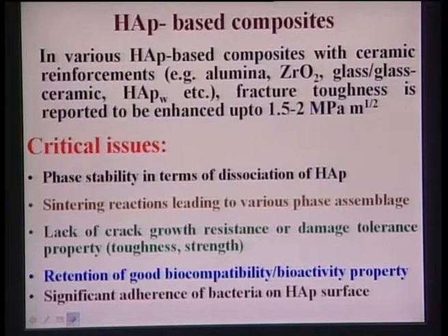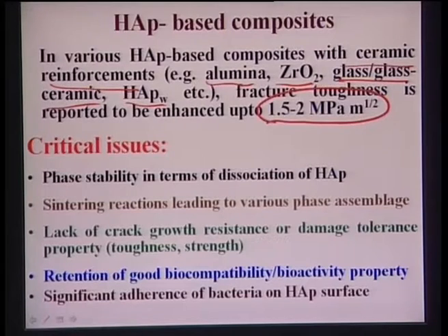Now, in various hydroxyapatite composites, particularly with ceramic reinforcements like alumina, zirconia, glass or glass ceramic, or hydroxyapatite whiskers, fracture toughness is reported to be enhanced up to 1.5 to 2 MPa square root meter. Because, as you have noticed in the last slide, I have mentioned that hydroxyapatite fracture toughness is less than 1 MPa square root meter.